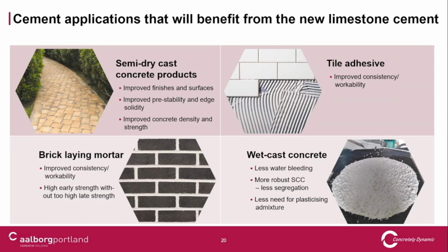What about wet cast concrete, precast concrete elements? We also expect this cement to have a beneficial effect here, mainly in self-compacting concrete. What we know from our present cement is that the tendency to bleeding and segregation when making self-compacting concrete can be a challenge. But now with around 15% finely ground limestone, we will have a more robust, less segregating, less bleeding concrete, which will be good for concrete elements.